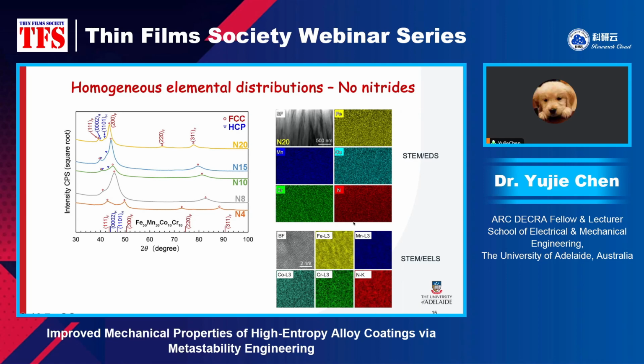So we can see that all these results indicate homogeneous elemental distribution, and there is no nitride formation. Even if the nitrogen content for this one, N20, we know the nitrogen content is as high as 29 atomic percent. So these alloys are not yet nitride, but should be described as dissolved solid solution, supersaturated with nitrogen. So the conclusion from this slide is that no nitride formation. They are just a nitrogen supersaturated solid solution phase.